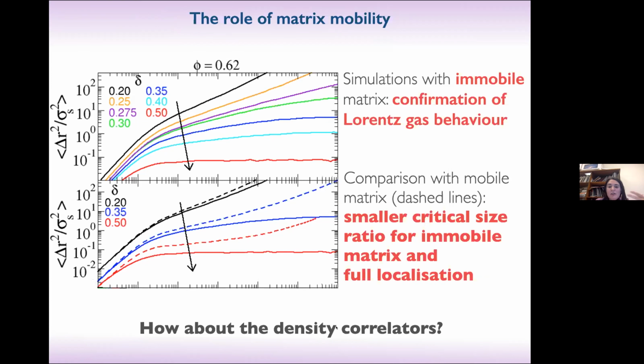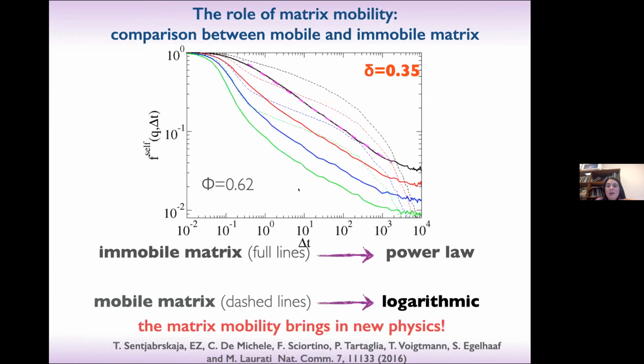And so how about the density correlator? I showed you before that these were logarithmic, and then we calculated also the ones for the immobile case at 35, and we found the confirmation of what we knew already, that in the immobile matrix the dependence of the correlator is power law, while in the mobile matrix it is logarithmic, as I showed you before. So the matrix mobility in the modified Lorentz model is able to bring this new physics, where the logarithmic dependence of the density correlator comes from a subtle interplay, this time not from two arrest mechanisms, but from this localization and the fact that this matrix can move. And we don't have currently a theory to explain these simulation and experimental findings.